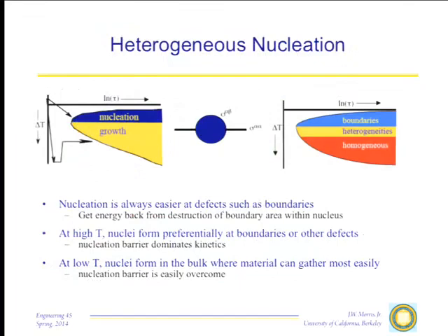The important thing to remember about nucleation and growth transformations is that their kinetics are given by a C-curve of the sort like it appears here. There are two interesting features of this C-curve. One is that it does have a nose. There are, well, three things really. First of all, it is always necessary to have some undercooling in order for a transformation to happen. Transformations do not happen at the melting point or the phase transformation point. They happen after some further undercooling.